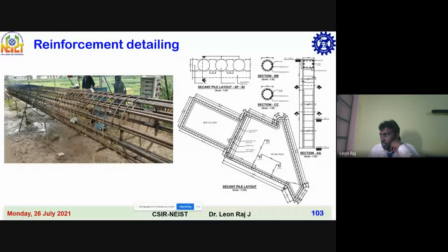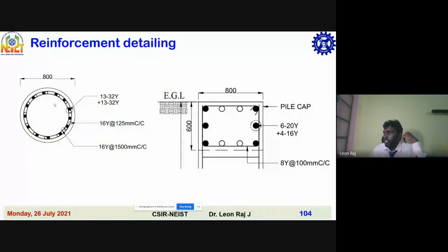So this is the concrete cover that was provided. Ductile detailing was planned according to IS 13920. Close spacings were provided, and splicings were not provided in the critical sections, not near the strut zones. And here you can see 16 bars of 16 mm diameter provided at 125 mm spacing, and the inner ring, that is the supporting ring, 16 mm diameter bar was provided at a spacing of 1.5 meters. Then longitudinal reinforcement is provided as 13 bars of 32 mm diameter plus 13 bars of 32 mm diameter. Two bars were provided.